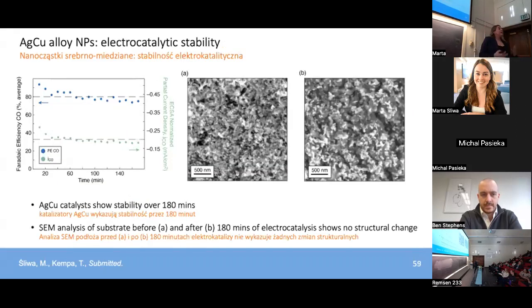Cu-rich phases as we hit that sort of solubility limit of the copper within our systems. So it's clear from the previous studies that the 5% copper and silver alloy is the best performing nanoparticle in our system. Having established that, we then went on to look at the stability of these 5% silver copper alloys. We performed 180 minutes of catalytic cycling and measured the Faraday efficiency as well as the partial current density for these carbon monoxide products over that time, and saw no appreciable drop in that activity or selectivity as we cycled the catalyst over and over again.